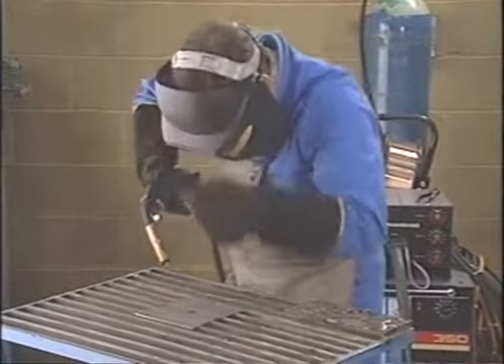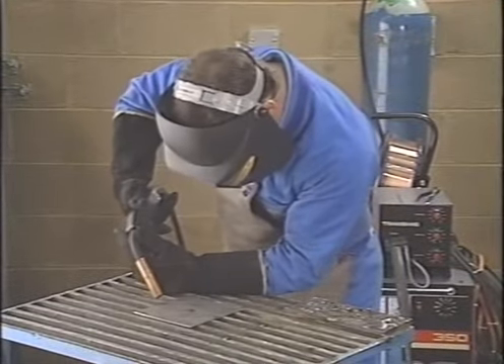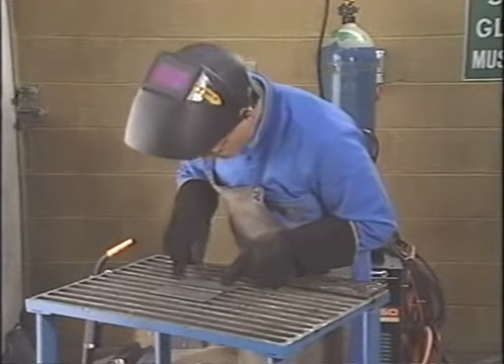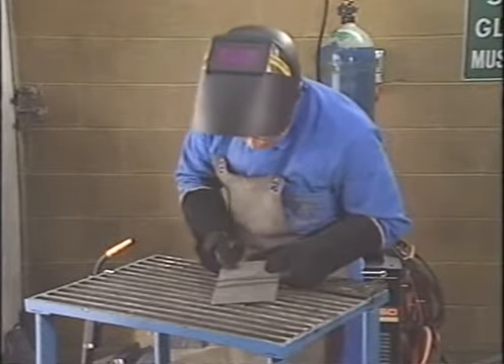Using the short arc transfer method and a gun angle of approximately 45 degrees in the direction of travel, commence welding. Move along the line of the weld. When you have completed the weld, break the arc cleanly. Check the work to ensure adequate penetration has taken place.